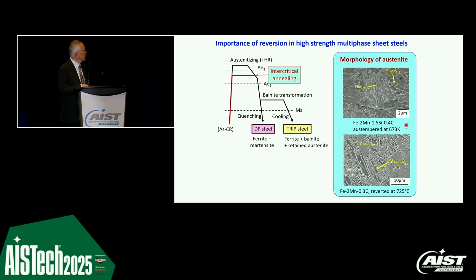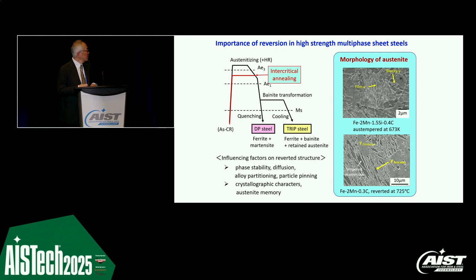And also for the reversion case, we have the granular one and also the acicular one, depending on the initial structure. We have different kinds of morphology of the reverted austenite. That kind of morphology is dictated by the crystallography of the phase transformations. And that morphology affects the phase stability and diffusion or alloy partitioning. And that is the same for the reversion case. And the crystallographic character is very important.